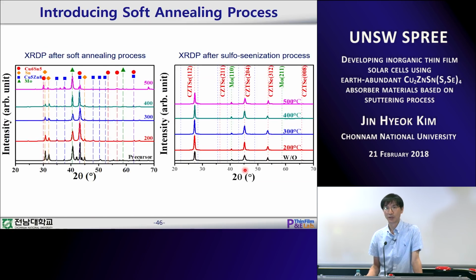This is the X-ray result after the soft annealing process, and then after the sulfo-selenization process. You can see that this is a precursor, but with increasing soft annealing temperature, you see the formation of alloy, mainly copper tin and copper zinc alloy. Even though we soft anneal the samples up to 500, we observe that there is tin left. But anyway, we form copper tin and copper zinc alloy.